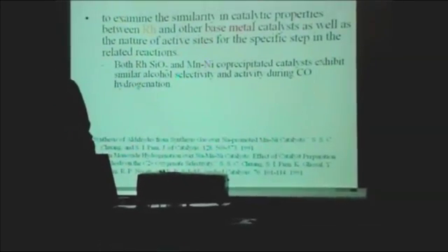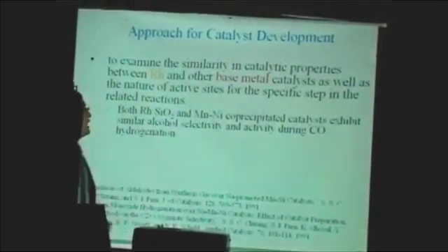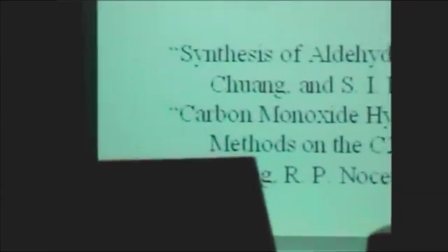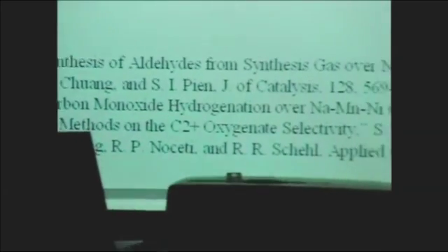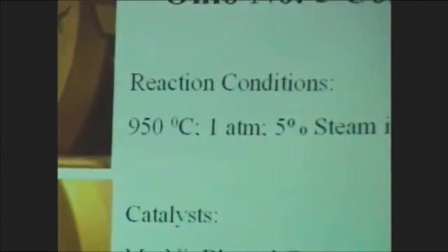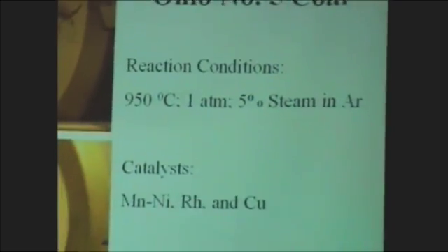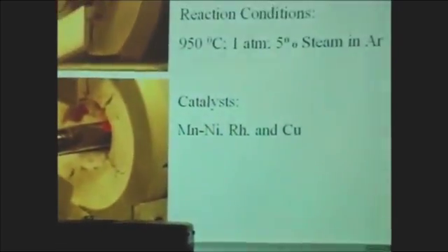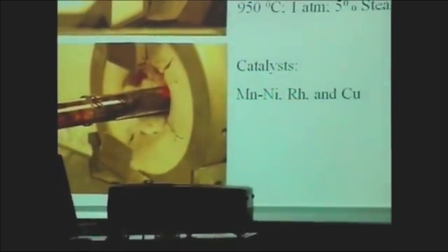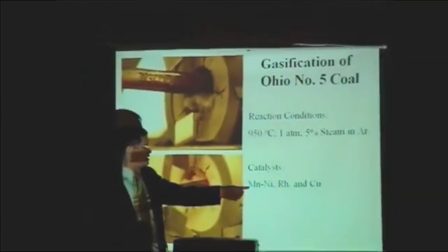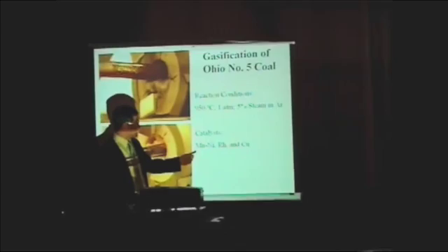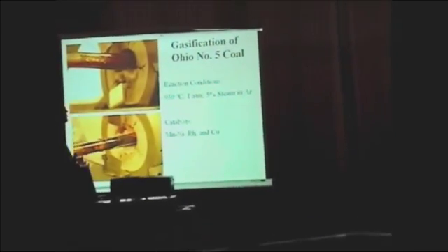We take this sodium manganese nickel catalyst, which is a coprecipitated catalyst, which showed very good activity in alcohol synthesis from CO hydrogenation. And we're going to test this catalyst to see whether it works well as a reforming catalyst for the coal or not. So this is the data we collected. This reaction is carried out in a high temperature oven, and we take the coal and heat it up at high temperature. We generate a lot of tar. And the idea here is to see whether this catalyst can reform the tar and also reform the coke or not. The catalyst is a manganese nickel catalyst, and this catalyst is prepared by coprecipitation. We start with nickel nitrate, manganese nitrate, and add sodium carbonate. So the final form of the catalyst in fact is a manganese oxide and nickel oxide form, and also a lot of sodium carbonate formed together.